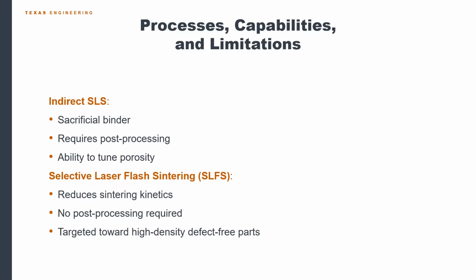The first one is indirect selective laser sintering, where we add a sacrificial binder so that when we scan it with the laser, only the sacrificial binder melts and forms bridges between the ceramic particles. This method does require some post-processing, but we have the ability to tune the porosity, and I'll talk a little bit about that next.